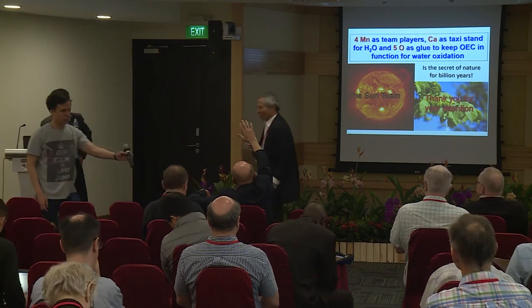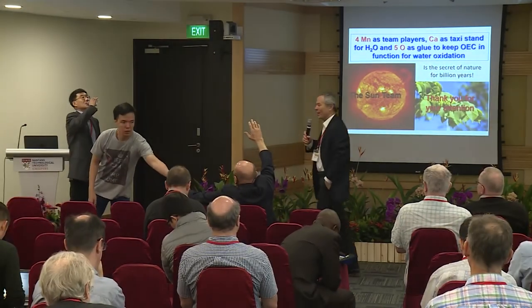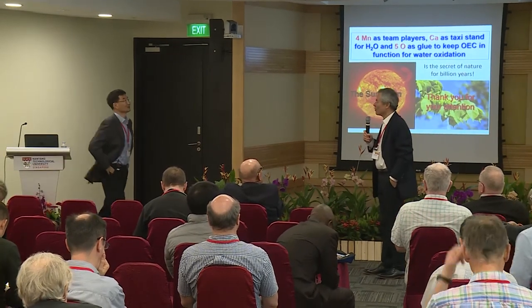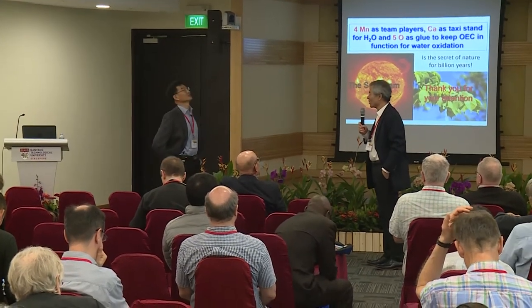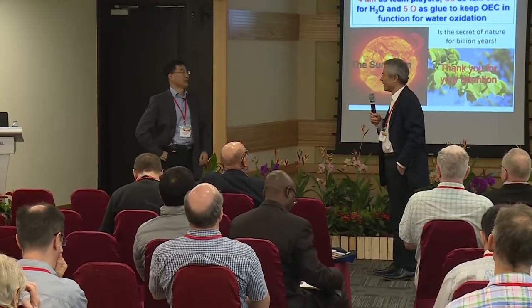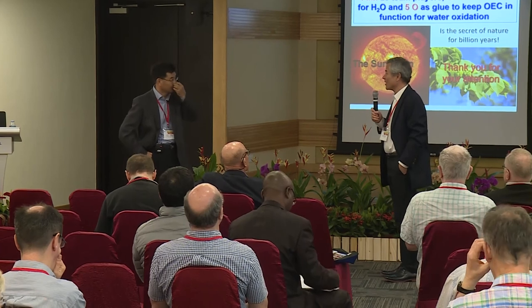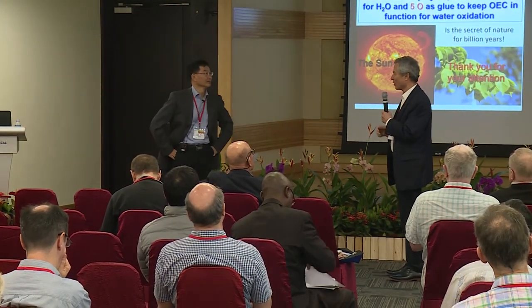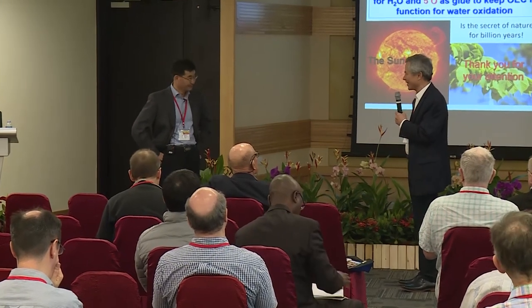Well, that will certainly promote some discussion, but maybe I can lead off with a couple of comments. So we actually published a paper in the 90s where we saw our manganese complex that disproportionated to make permanganate. But we viewed this as a deactivation process because the permanganate formation correlated with loss of water oxidation activity.